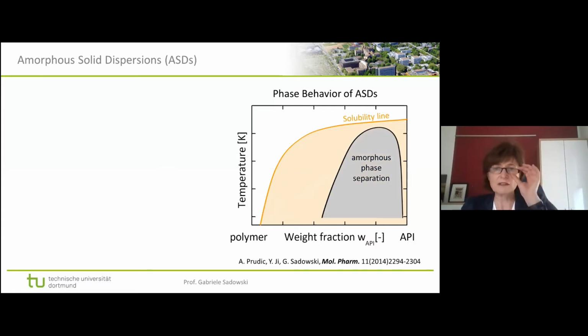Now, on top of this, you see what the pharmacists call amorphous phase separation. From a thermodynamic point of view, it's nothing else than a liquid-liquid demixing. And of course, you know that you have a binodal here, and that on the two branches of the binodal at a given temperature, you get the concentrations of the two phases. So that means once you are here, your tablet would phase separate.